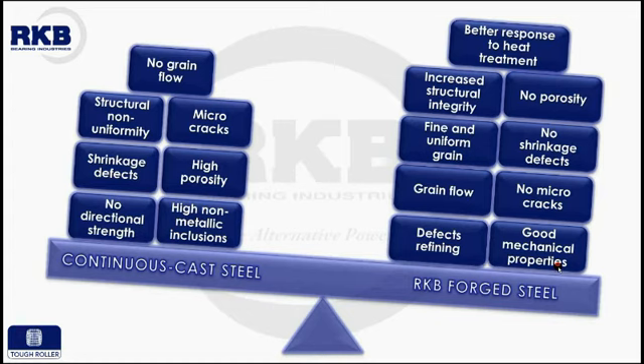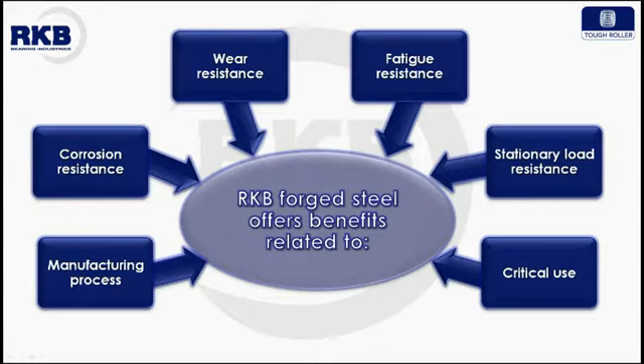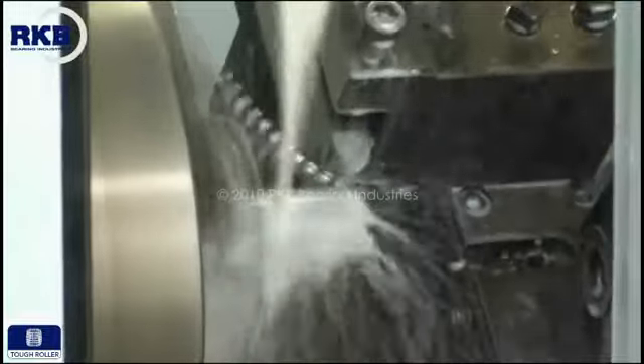The typical uniform hardness reached by RKB Tough Rollers varies between 61 and 63 HRC. The forged steel used by RKB for the manufacture of its tough rollers offers benefits related to the roller manufacturing process, the corrosion, wear, fatigue, and the stationary load resistance, and the use in critical applications. The forging process gives our tough rollers a degree of structural integrity that cannot be achieved by the continuous casting process and enables the correct performance of machining and heat treatment operations.